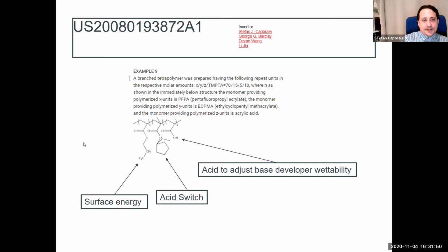So we realized we had to have some acid in there to let the water wet it enough, again, to tune that angle, because we don't want it completely hydrophobic to push all the water away, kind of like Rain-X on your car window. It has to touch the water somewhat, because we also don't want air gaps or bubbles forming along that, because that would scatter the light and cause defects. And then again, the leaving group in the switched areas to have good wettability. So again, this is pulled directly from our patent application, and is an example of one of the materials we use.